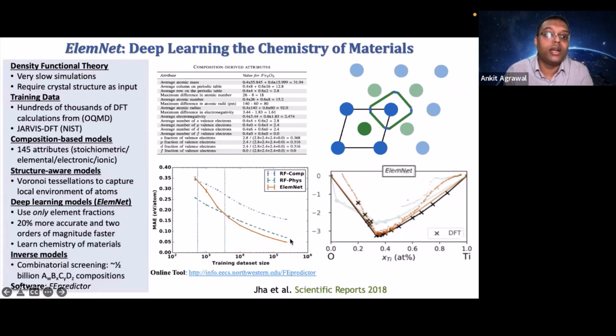And then we also found that it learns the chemistry of materials in some sense, because the model somehow knew that sodium, potassium, cesium, lithium, these all belong together, although we did not give any valency, atomic number, nothing. When we tried to do some interpretation of the model using activation analysis and so on, we found that it is treating those elements together. And it also knew that group 1 and group 7 in a 1-to-1 ratio will give a stable compound, and group 1 and group 6 in 1-to-1 ratio will not. So it was quite fascinating that the model could just self-learn this chemistry by itself.